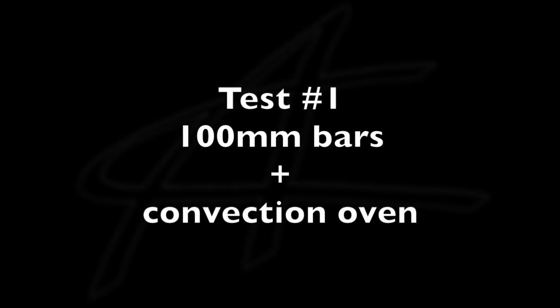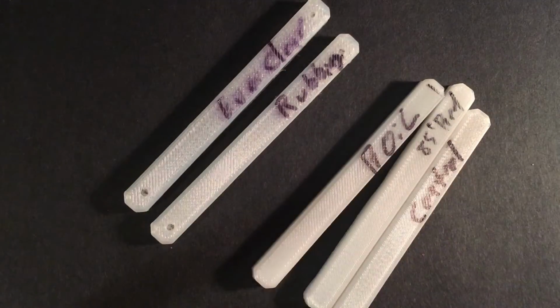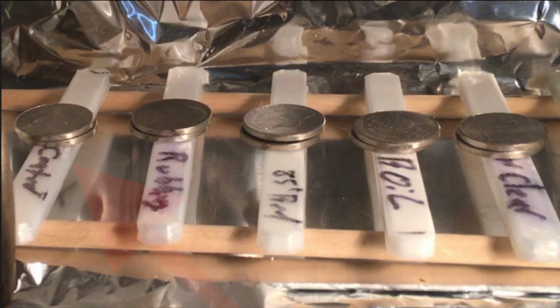And third, I'm going to blow through all these tests, just show you fast forward pictures of the melting process and talk over it. Then we will discuss the results at the end just to save time and keep everything nice and tidy. So the first test was the 100mm bars with the 50% gyroid infill. They were all treated with either the Everclear or rubbing alcohol at ambient temperature for an hour. They were boiled or put on an 85-degree bed for an hour, and then there was the control all the way to the left there.